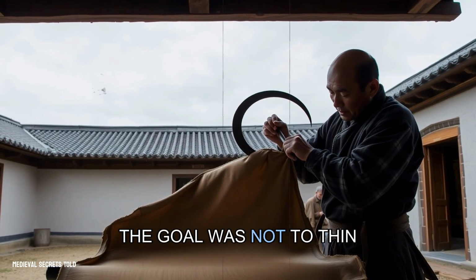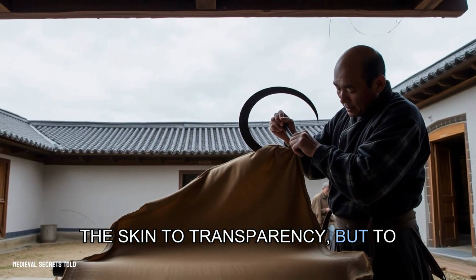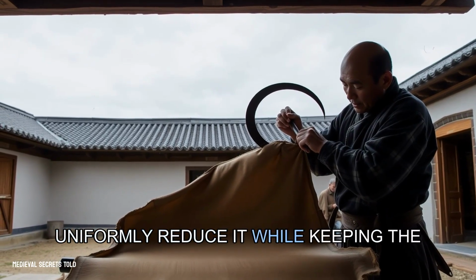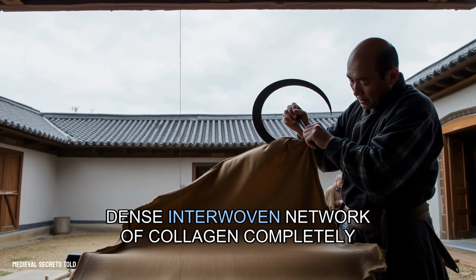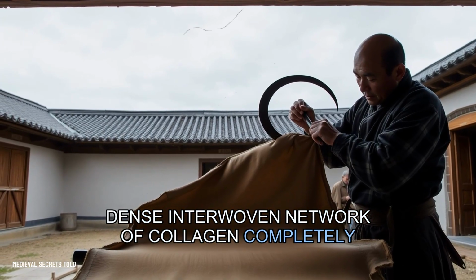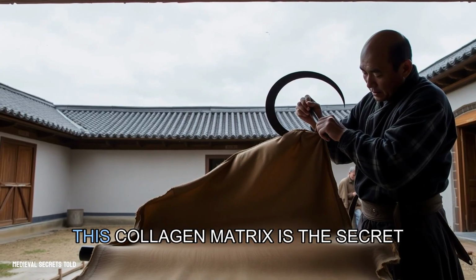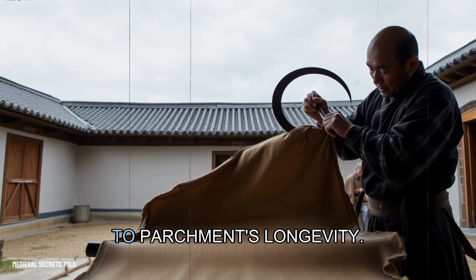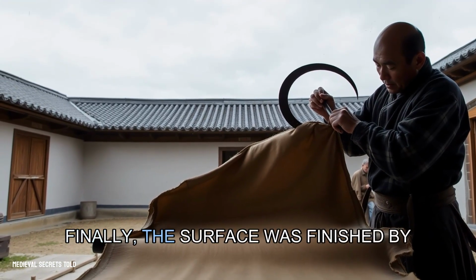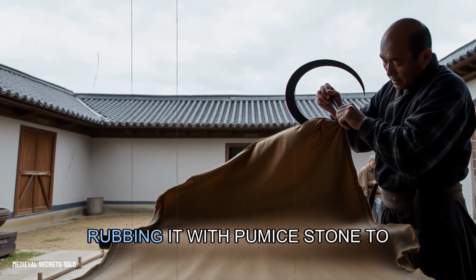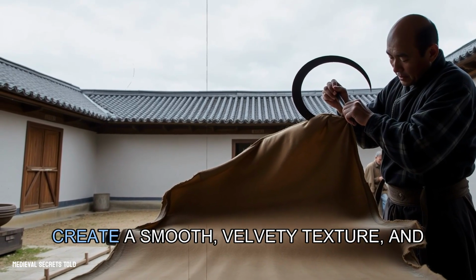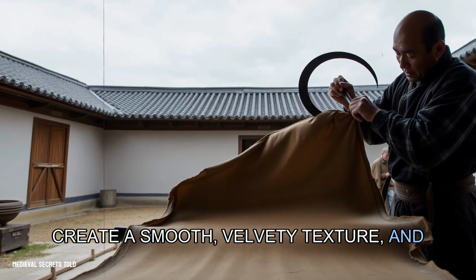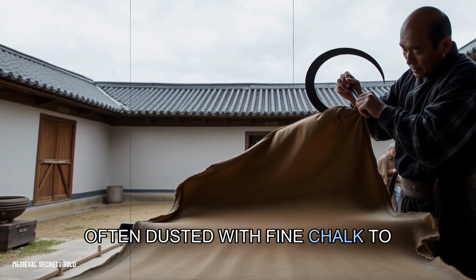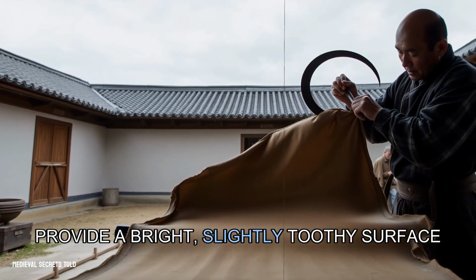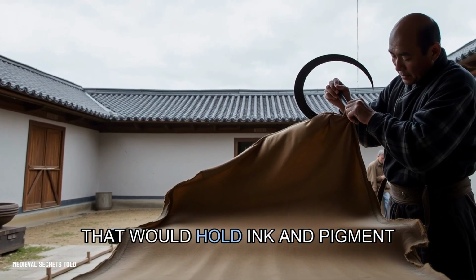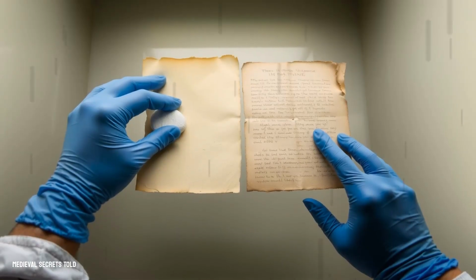The goal was not to thin the skin to transparency, but to uniformly reduce it while keeping the dense, interwoven network of collagen completely intact. This collagen matrix is the secret to parchment's longevity. Finally, the surface was finished by rubbing it with pumice stone to create a smooth, velvety texture, and often dusted with fine chalk to provide a bright, slightly toothy surface that would hold ink and pigment without bleeding.